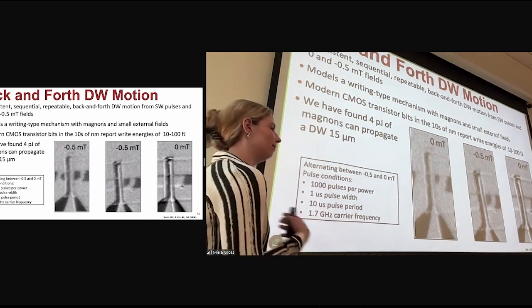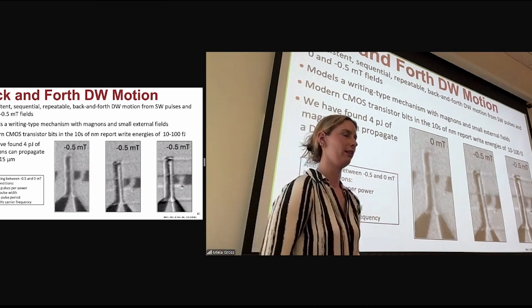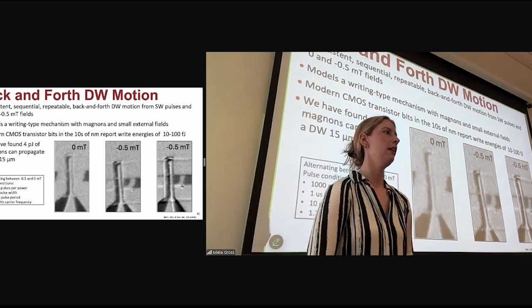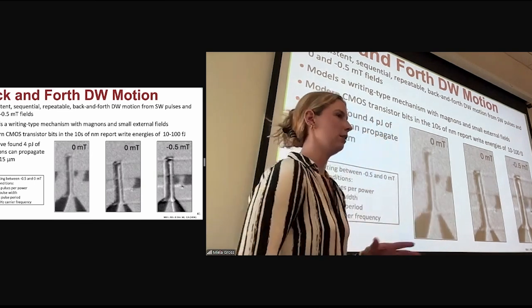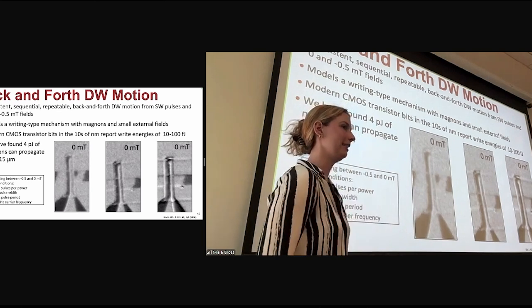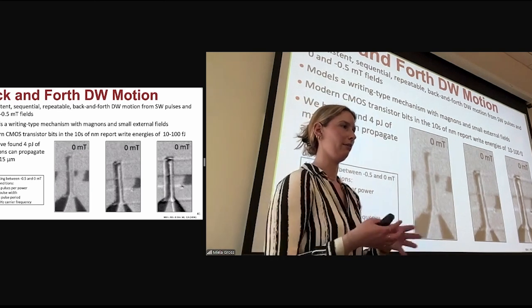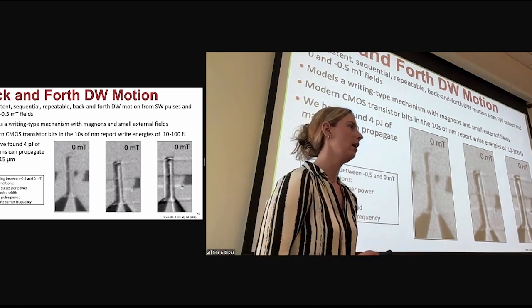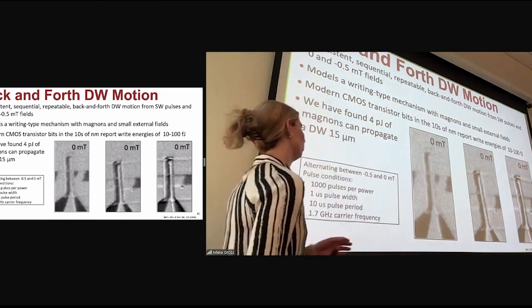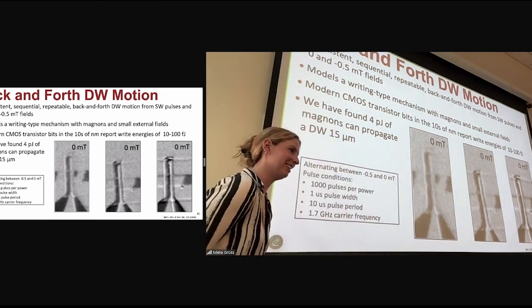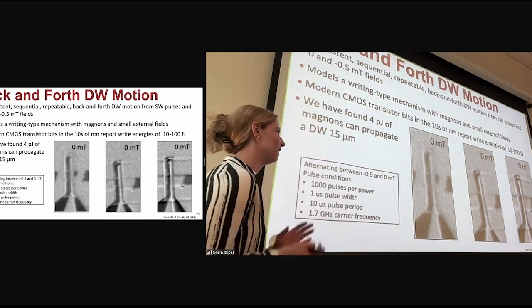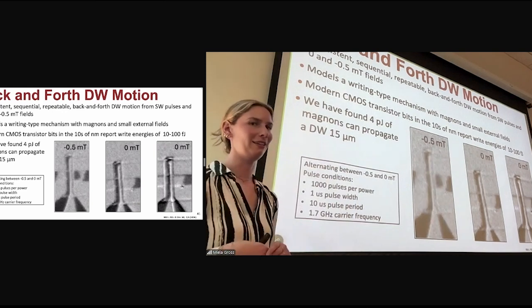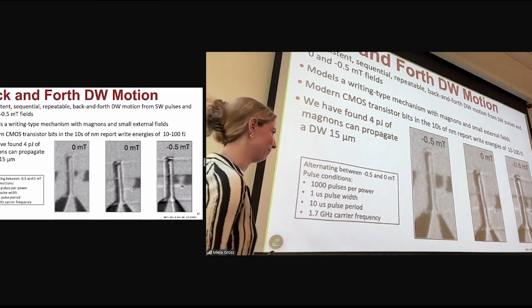And if we were to look at modern CMOS transistors that are on the size of tens of nanometers, they use about 10 to 100 femtojoules for write energies. If we were to downscale this effect to a similar size, we would be using 4 femtojoules of energy instead of just 4 picojoules. So still a pretty significantly low energy mechanism.